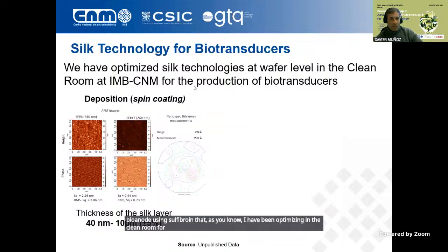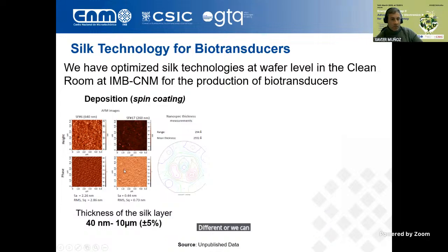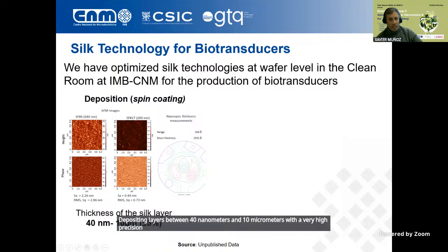Now we have a silk technology at wafer level where we can deposit silk fibroin in a very controlled way, depositing layers between 40 nanometers and 10 micrometers with very high precision. The difference in these layers is less than 5% across the whole wafer.